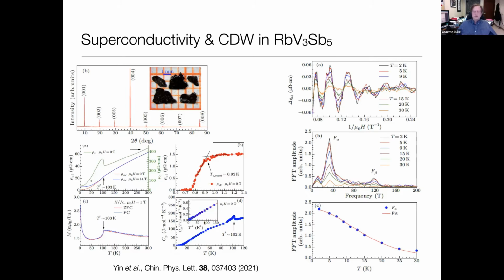These materials are very clean, so they're very good metals, in fact. And so here you can see Shubnikov-de Haas oscillations, which tell you that you really are dealing with fermions in there. The samples must be extremely clean for you to see these coherent quantum oscillations. And from that, you can see things about some of the parts of the Fermi surface and the extremal Fermi surface orbits, and you can get things like the effective mass from the temperature dependence of these orbits.